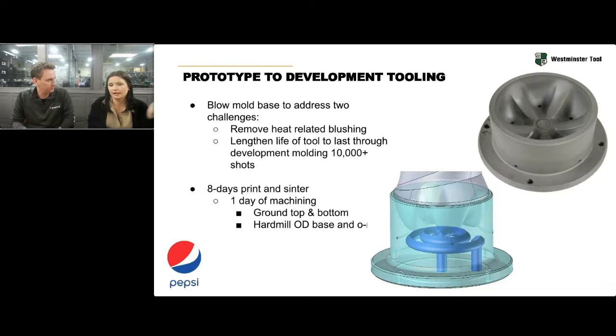I will say the 8 days was done early on, when we received our beta printer. Since doing this project, we've reduced print times by about 30%, so this would probably run closer to a 5 to 6 day print at this point. But again, this was a really big way that they were able to still accomplish the speed they needed for the first step, and to bridge into their automation simulations.